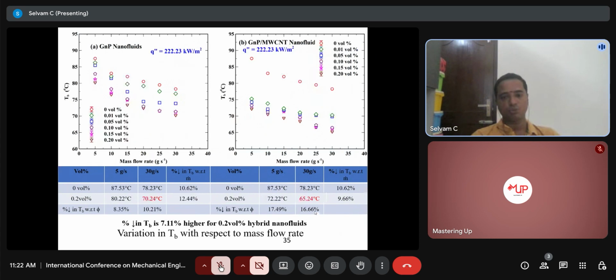And this is another graph with respect to the higher heat flux. Here the hybrid nanofluid shows higher variation. You can see from 87.5 degrees Celsius the temperature is decreased up to 70.24 with graphene, and from 87.53 it is decreased up to 65.24 degrees Celsius with the use of hybrid nanofluid. So it shows that the hybrid nanofluid is significant.